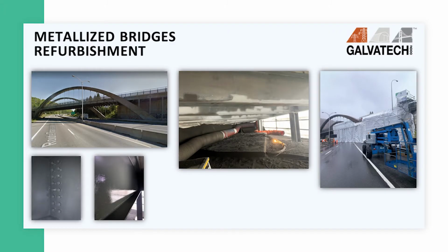It merges with old zinc layers to recharge the cathodic protection of the galvanized steel, all in one coat. It's perfectly adapted for maintenance projects. Here it is, used as a sealer and top coat on metallized steels. It also penetrates the surface irregularities without leaving air voids. It merges with the metallized layer to increase the massive zinc and prolongs its service life.